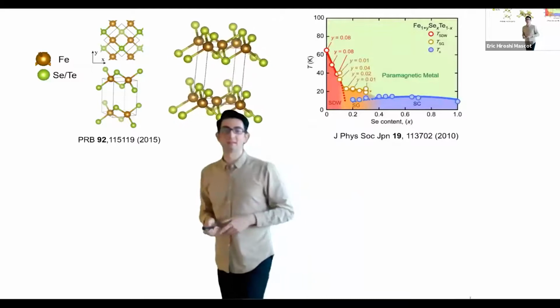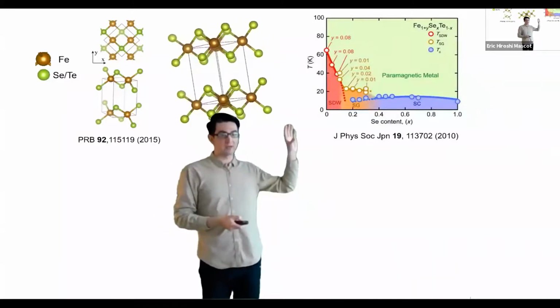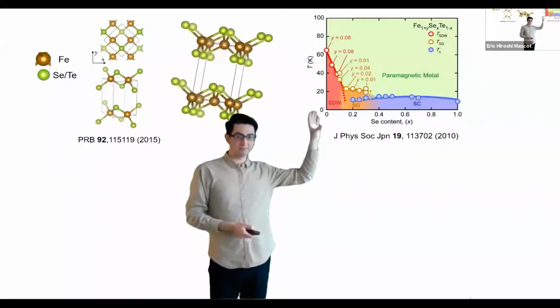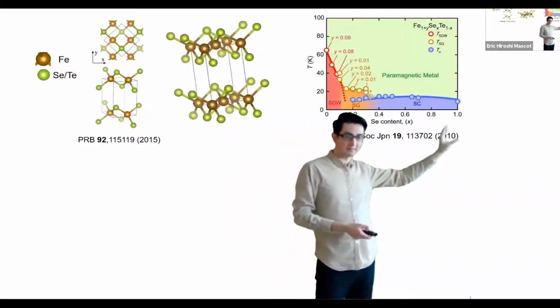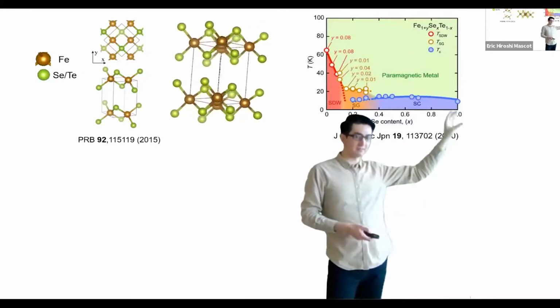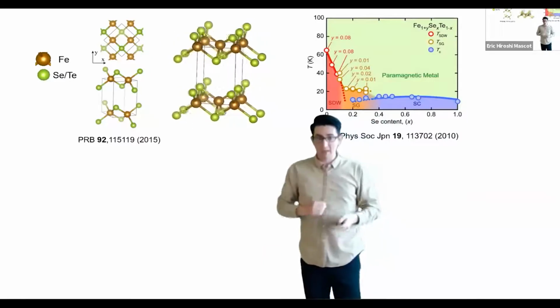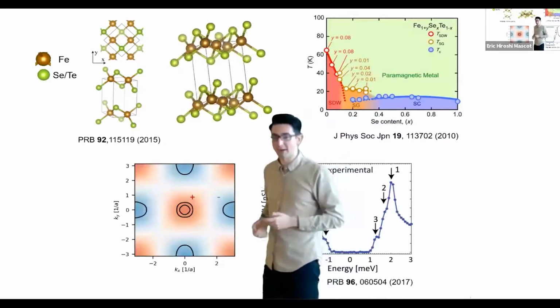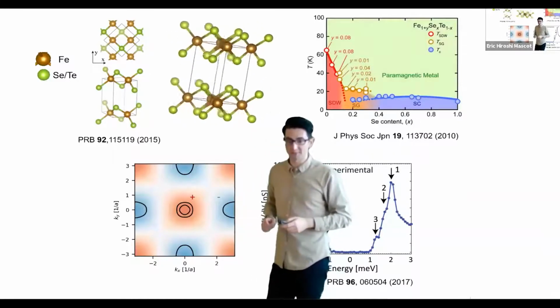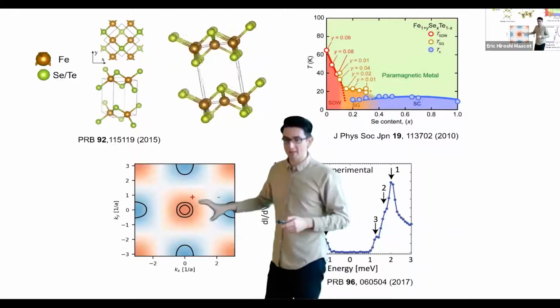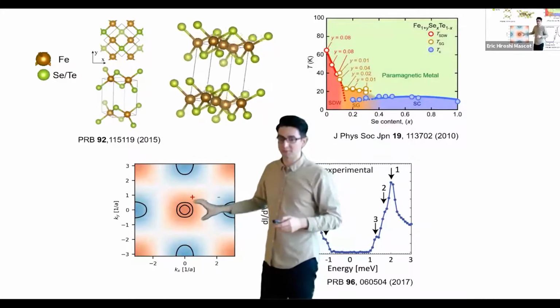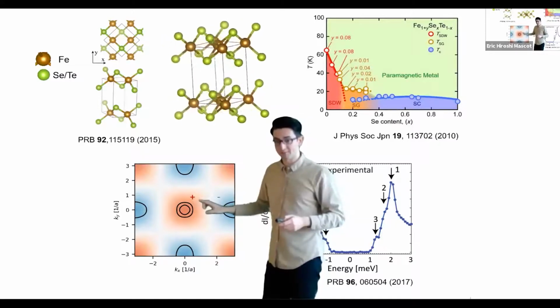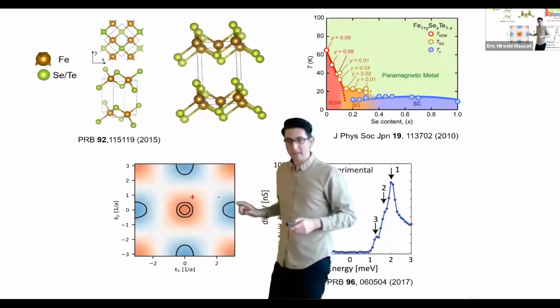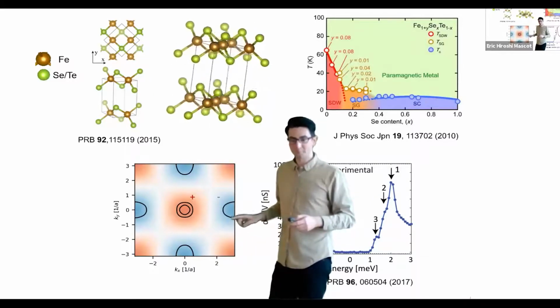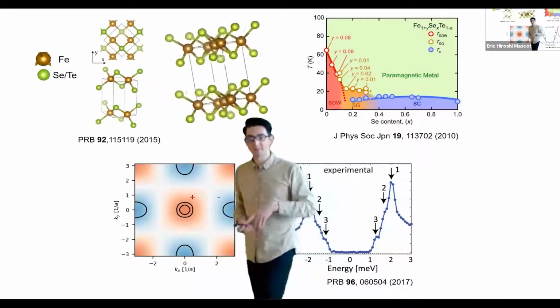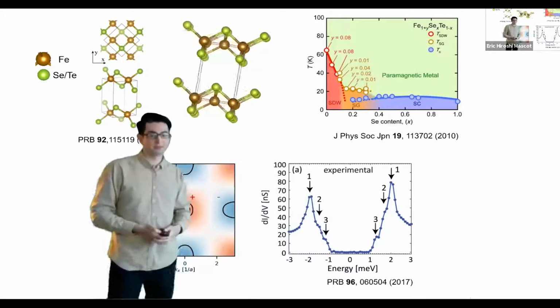And it has this kind of phase diagram for different doping. On the iron tellurium side, we get a spin density wave. And as we go to the iron selenide side, we get a superconductor, which has a TC of around 10 Kelvin. And the superconductor is interesting. It has an S plus minus wave symmetry. So here's this Fermi surface in the normal state. And in the center, we have these two Fermi surfaces, and the superconducting order parameter here is positive. And then on these edge Fermi surfaces, the superconducting order parameter is negative. So it's an S plus minus wave symmetry.